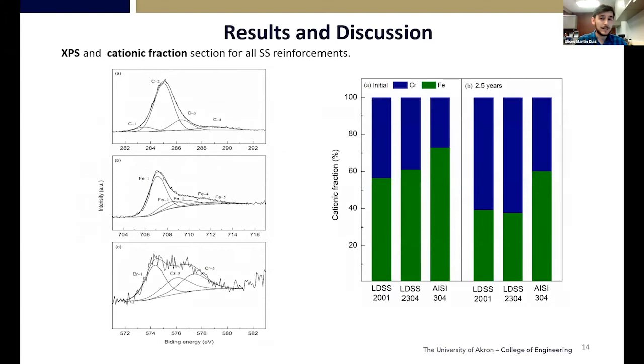Finally, we did some XPS analysis at the beginning of the testing and after 2.5 years. We saw that both lean duplex had an increase of 20% of the cationic fraction of the chromium compared to only 10% for the 304, showing that towards these 2.5 years, this chromium layer was being increased and enhancing the protection, as we've seen by the Isgor and Akron monitoring, as well as being a very stable passive film and protectiveness seen on the impedance.